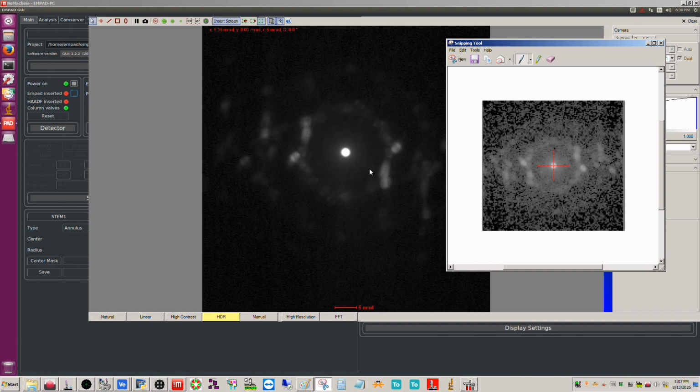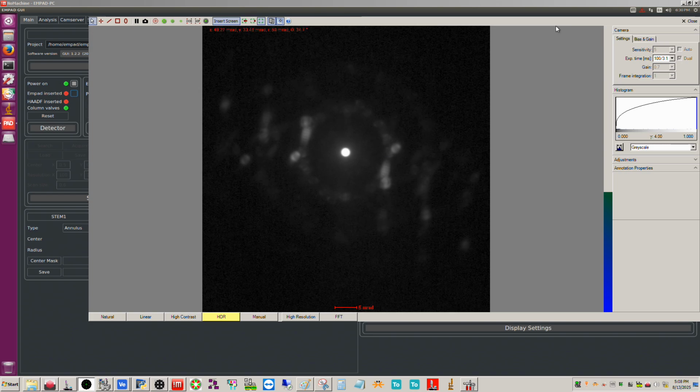If you're trying to establish the DP relationship with the image, you actually need to flip the DPs upside down. Not rotate, mind you, flip. You need to flip upside down in order to get the proper orientation with the actual sample itself. So that's something important that I didn't point out when I did this yesterday.